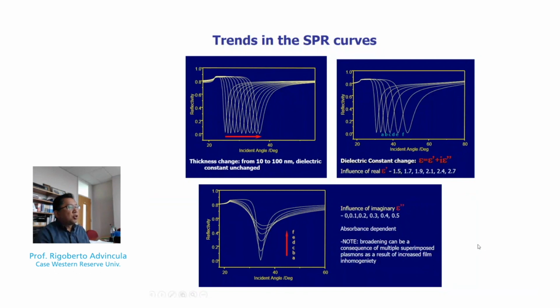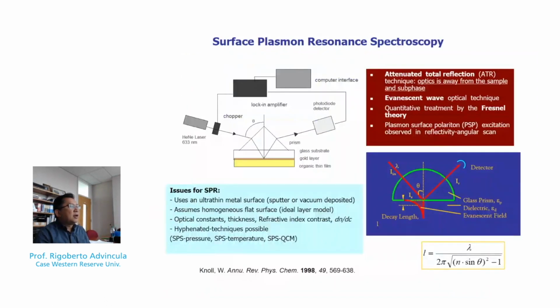Another is that absorption changes, which is more of the imaginary part of the refractive index. Let's say if you change the absorption from 0 to 0.5, you see here that the dip in the curve changes as well. And as you increase the imaginary part of the refractive index, the dip becomes shallower. So that means we can actually do some modeling or simulate the SPR curves.